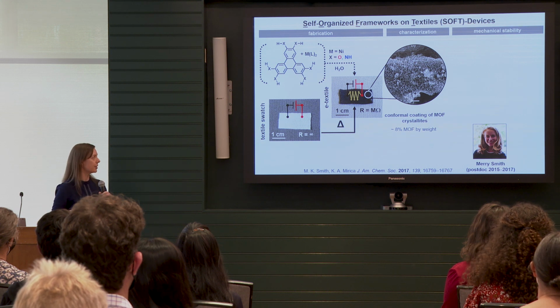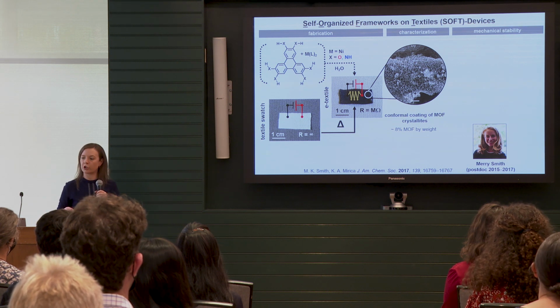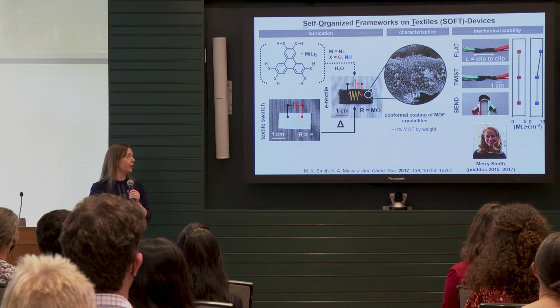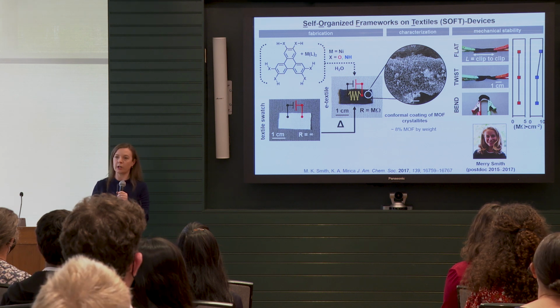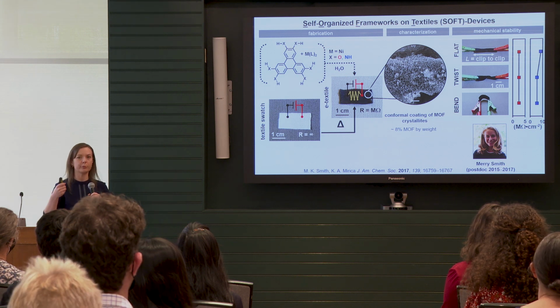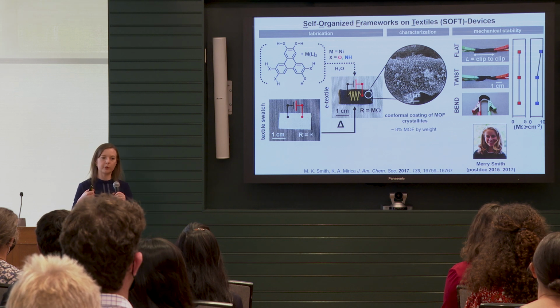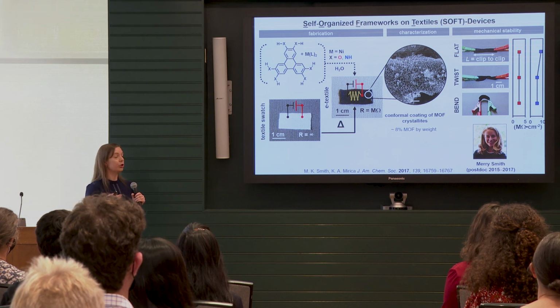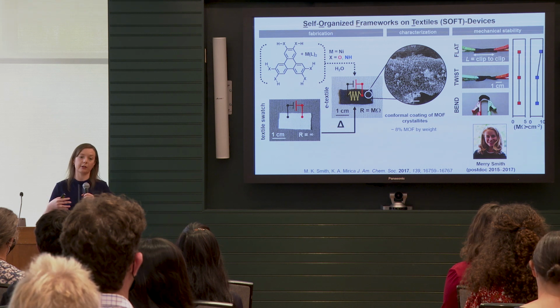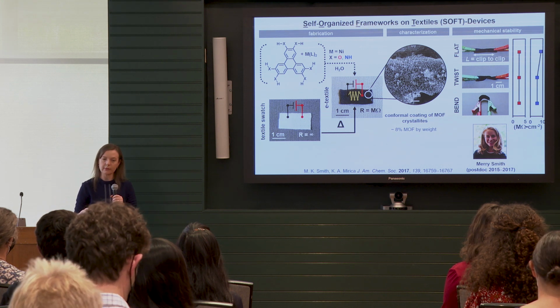such that we get conformal coating of the cellulose fibers by the metal organic framework crystallites. And this generates an electronic textile that has very good, robust performance, where its electronic properties are unperturbed by mechanical perturbations, which is good because we want a chemical sensor. We don't want a mechanical or strain sensor.